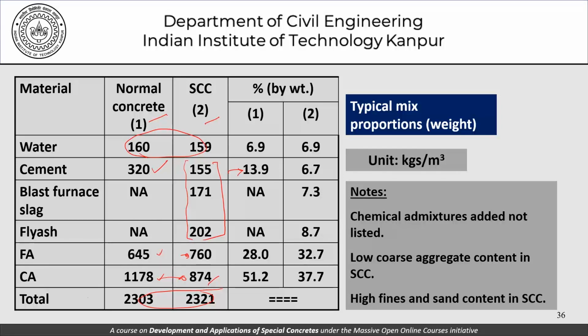That is translated here in terms of weight percentages. From 51%, the aggregate content is only 37-38%. The sand has gone up from about 28 to 32, but the issue is here. So this is much larger than this value here. That is the crux of getting self-compacting concrete or self-compactability in concrete.